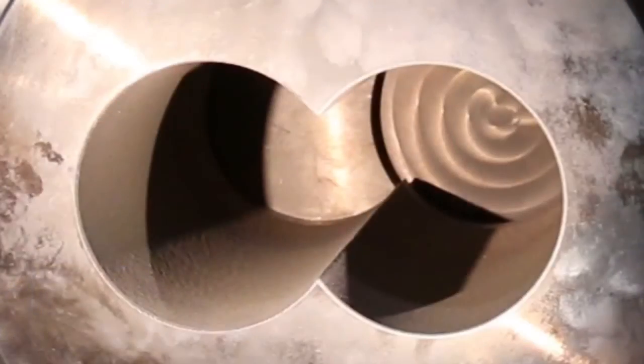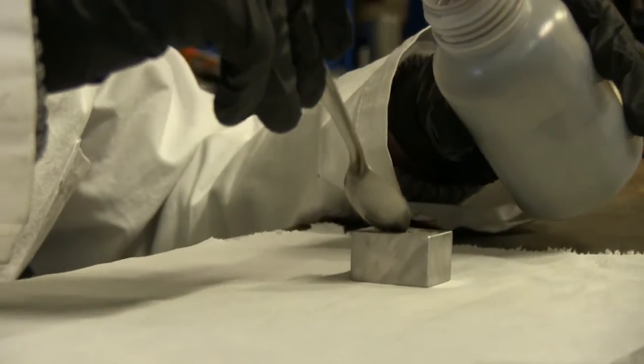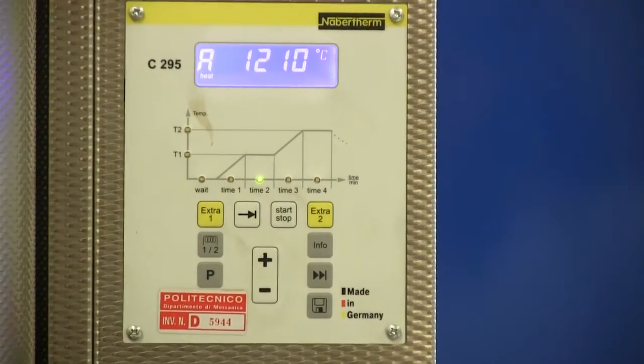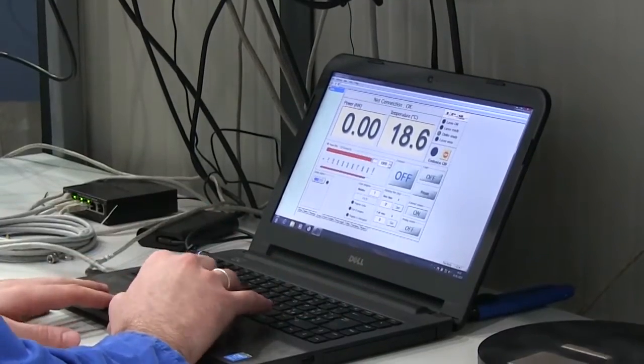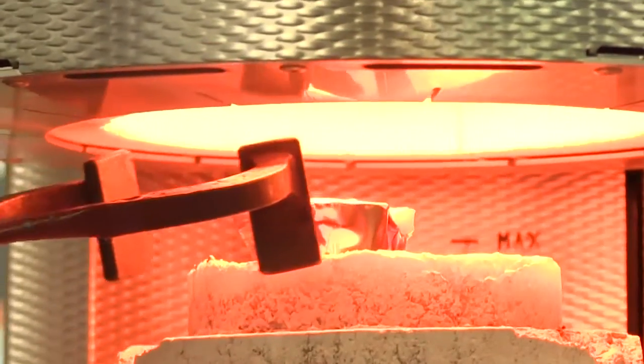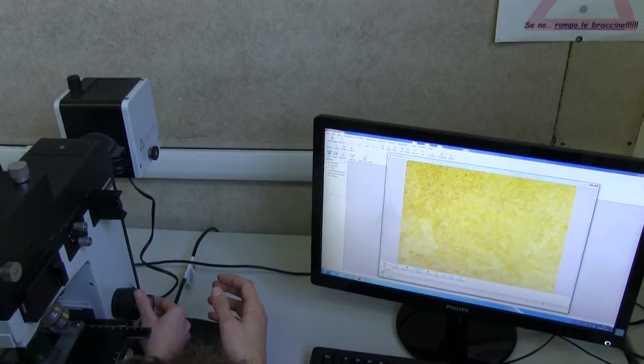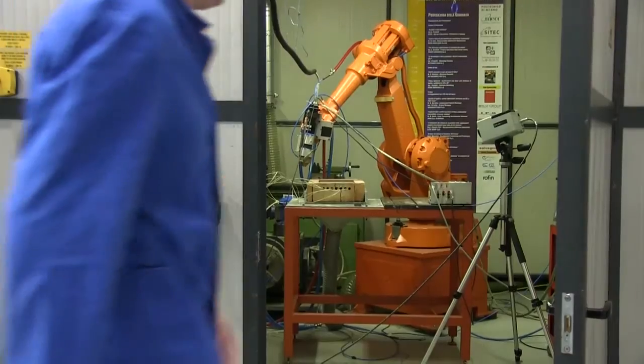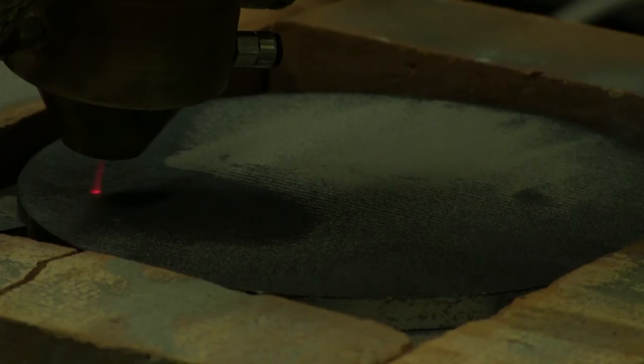Barrels are internally coated to obtain bimetallic barrels by spin casting or by laser cladding. Research actions have been undertaken to develop new alloys for the spin cast coatings. Alloys have been first studied by laboratory experiments to simulate the behavior of the material and the effect of dilution and casting during processing of bimetallic barrels. Castings of small volume samples have been performed to analyze material structure and properties such as hardness, wear behavior, and corrosion resistance.